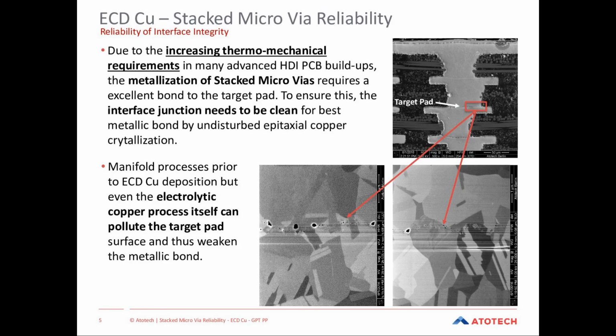So nanovoids can originate from electroless copper deposition. For example, if you have a lot of hydrogen evolution at the target pad, it might be that some of this hydrogen in its adsorbed condition will stay there and get co-deposited and incorporated in the electroless copper deposit. And later, during a thermal stress application, this hydrogen can accumulate to smaller gas pores, and then it gets visible.